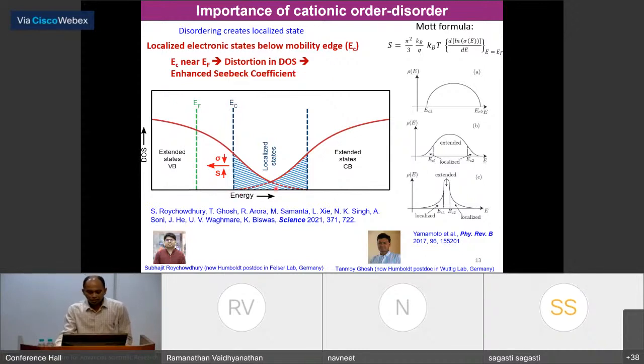Now from the famous Mott equation, you can see that the Seebeck coefficient is the first derivative of the density of states. When EC moves towards the Fermi level, the parabolic nature distorts and increases the effective mass, which increases the Seebeck coefficient. So if I move EC towards the Fermi level, electrical conductivity decreases and, at the same time, Seebeck coefficient increases. So there is a conflicting effect of disordering, because disordering creates these localized states. We cannot work in the regime of Anderson localization, because we would have an insulator with a high Seebeck coefficient, but we want good electrical conductivity. That's why we need to work in a partial ordering state, or rather the weak localization regime, so that we have delocalization of the electronic states and a good Seebeck coefficient at the same time.